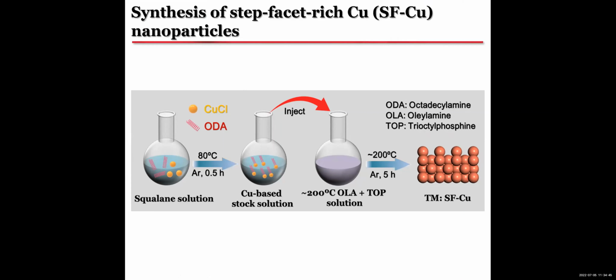copper nanoparticle. So we basically use a solution method, okay, at 80 degrees with the copper-based stock solution injected together with some organic solutions, ODA, TOP, and OLA, all of this, okay, so about 200 degrees. Then we can create these nanoparticles. We call it a step-facet-rich nanoparticle. Later on, we will explain why we actually call it SF copper.